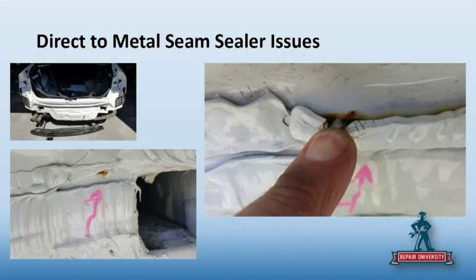And what happens is, from the picture, you can see that especially with a bead with a tall profile, like you're seeing there, you have a shadow side of the bead. And a lot of painters will only paint from one direction, probably because there's something in the way from the other direction. So the primer just kind of goes over and leaves a shadow on the back side where there's either no coating or very thin coatings. And that's where the corrosion starts, right. And that's exactly what happened here. Yeah, so in this case, you have to paint from both directions and be very thorough with your coatings.